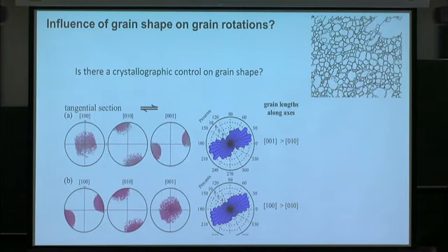All right. So Chow went ahead and made a bunch of these measurements looking at grain shape. To really understand it in 3 dimensions, you have to do it on a variety of sections, and we want to relate it to the crystallography. So we could take the crystal distribution, pick out just the grains in a certain orientation, and then look at the length of an ellipse fit to them. In this case, the 001 axes are longer than the 010 axes.